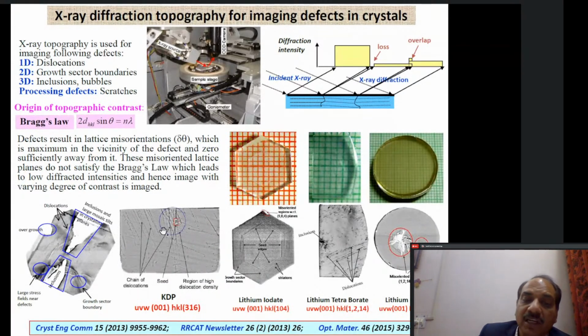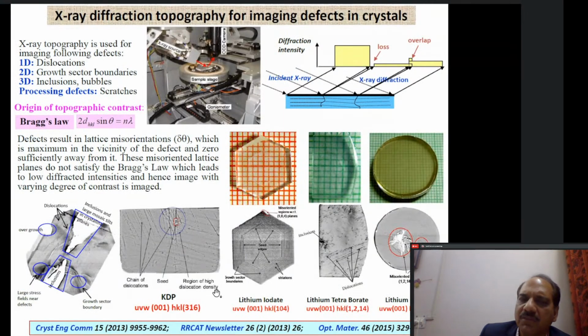You see, in case of KDP crystal, this crystal was appearing absolutely transparent. UV visible transmission was absolutely perfect, right? 80-90%. But once we did X-ray topography, we were able to see there is a huge dislocation near the seed crystal. And this is what is reported in literature also, that when you grow a crystal, the initial defects start generating from the seed crystal, but as you go away from the seed crystal, the crystal quality becomes better and better.